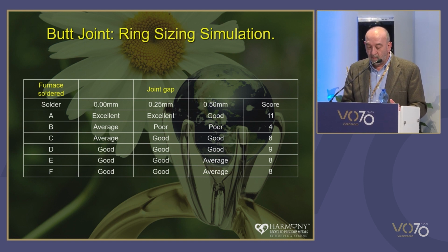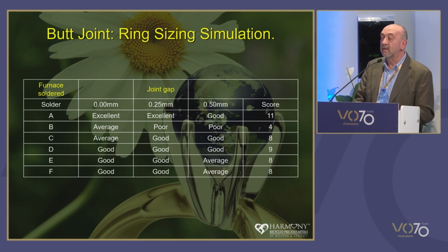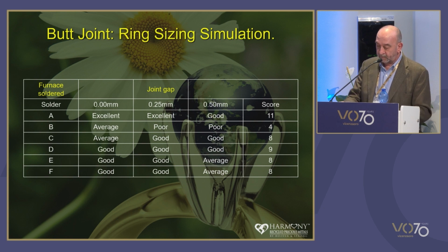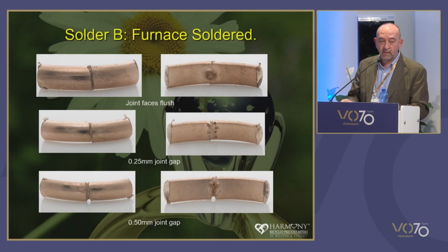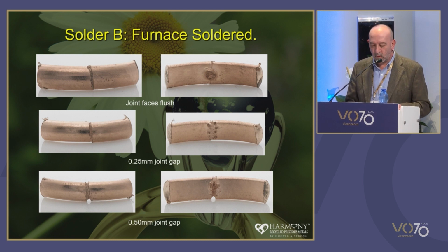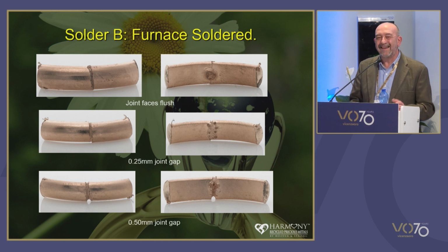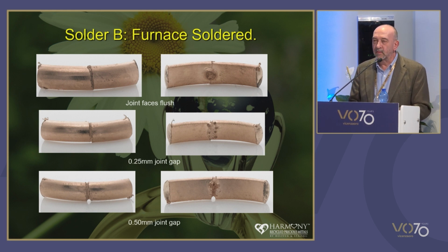Solder A performed very well, suggesting this solder is well suited to furnace applications, but the other solders did not, with solder B again having the lowest score. And we can see some of the joints here. As with the wetting tests, like I said, solder B had evidence of the residual solder being present, and it had very poor wetting and very poor flow. All the other tests were acceptable, but needed repair to achieve an acceptable standard.